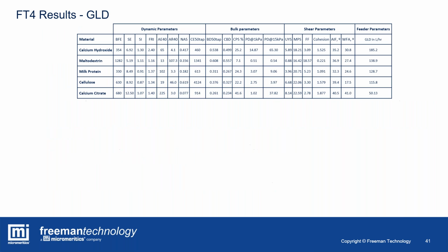So here we have a whole series of measured properties for the 5 materials, starting left-hand side here, calcium hydroxide, down to calcium citrate. You've got dynamic flow properties from the FT4, so the confined and unconfined dynamic flowability energies, the sensitivity to being measured or the stability of the sample, the strain rate or flow rate sensitivity, which is the flow rate index, the sensitivity of the material to aeration and also consolidation.